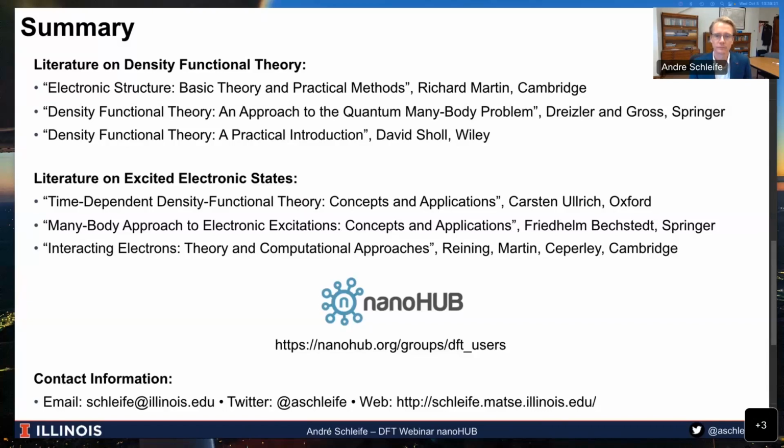All right, thanks. The next question, are there well-known materials for which simulations using these techniques are extremely inaccurate? So yes, well, that's a good question. I mean, known groups of materials, I don't think I'm the right person to necessarily answer that, but one thing that is challenging is a correct description of the electron-electron interaction. And so sometimes people cite materials that have very strong correlation effects as challenging. However, that is, I would say, a somewhat diffusely defined group of materials, meaning if you tell me a stoichiometric formula, I cannot tell you upfront, is this a strongly correlated material or not? And so we'd have to then look at the details. And on top of it, there are recent directions in literature that investigate disorder as the reason that sometimes can account for some of the disagreements that were previously attributed to a strong correlation. So I think that's not such an easy question to answer.